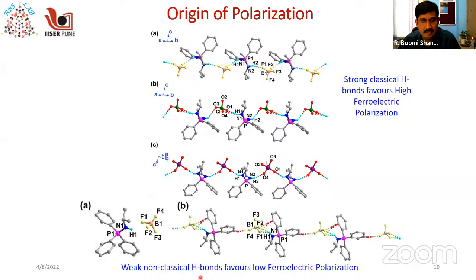Whereas in the case of this molecule, which has 3 phenyls and 1 amino group, it cannot propagate with strong interactions along the polar axis. There is a strong NHF interaction present in this molecule, which is forming a dimeric structure. However, these dimers are subsequently connected by non-classical CHF interactions, which means that the dipoles are separated at a farther distance, and the long range ordering of these dipoles is not as strong as in the other molecules. As a result, this molecule shows a very low ferroelectric polarization.